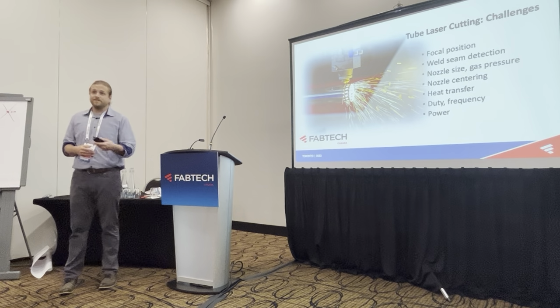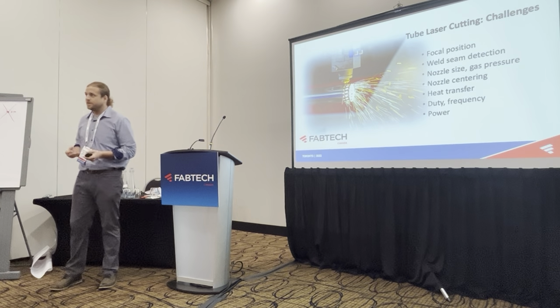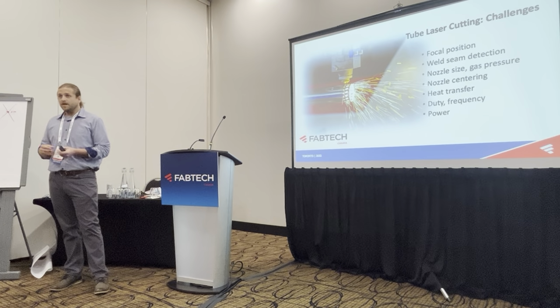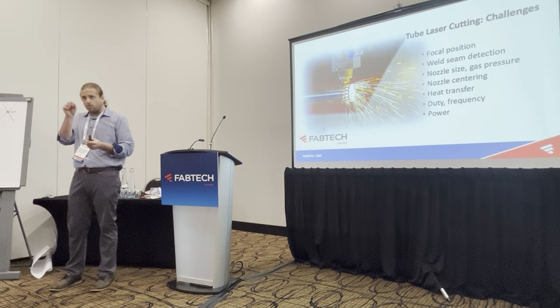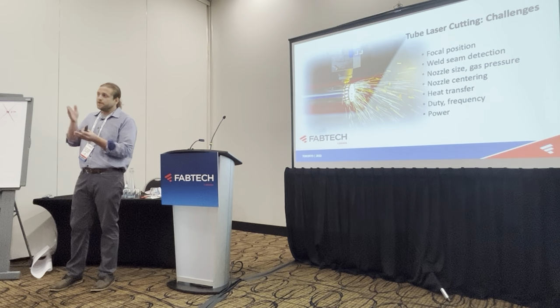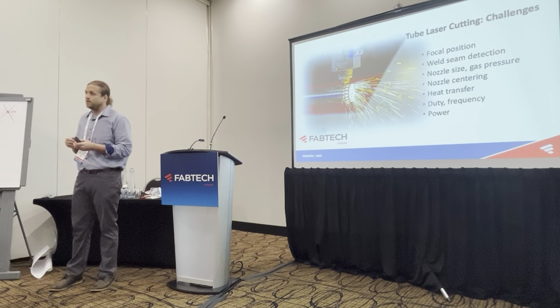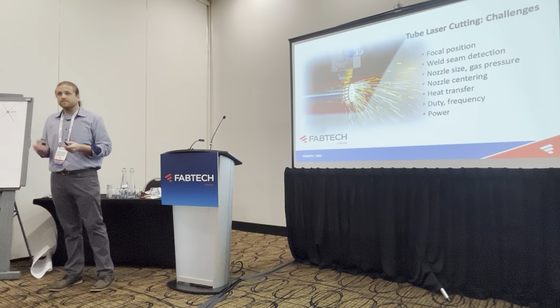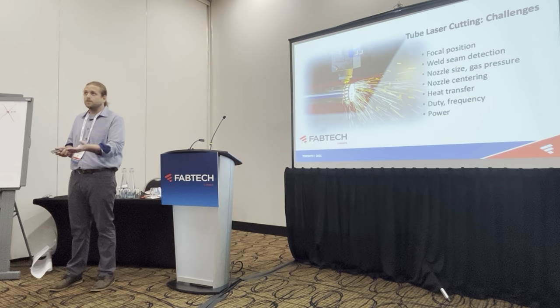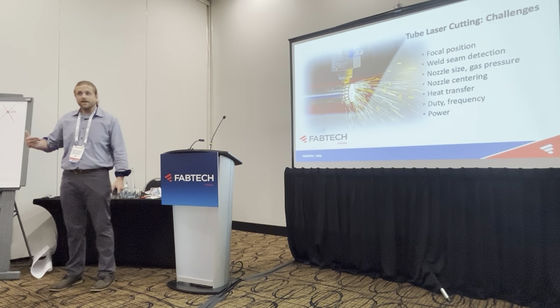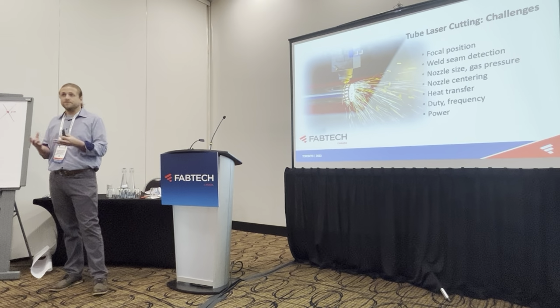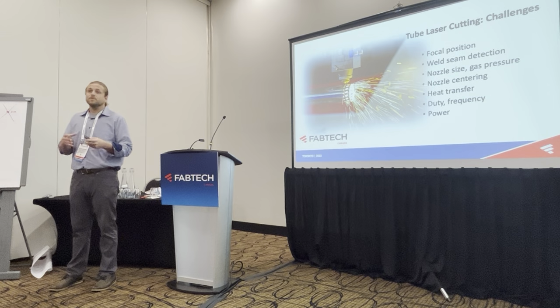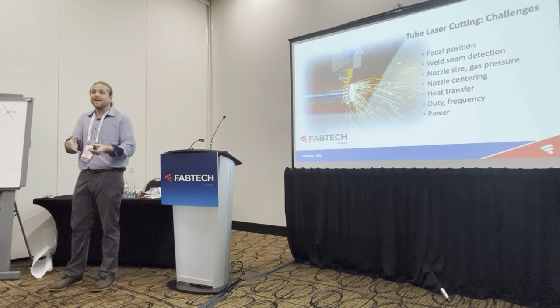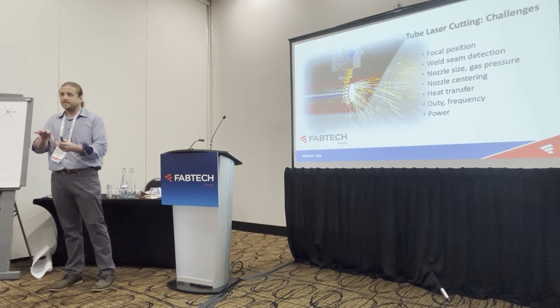Now aluminum, that's a different issue. Aluminum is a softer material, and as you're cutting it, it's really difficult to get rid of the burrs. With steel and stainless, you'll get a nice rollover bead from your dross. With aluminum, you get actual sharp cut teeth that you'll have to deburr, and you can't really eliminate them completely. You can dial your cut in to reduce them, but most of the time with aluminum, you're always going to have to do some kind of deburr operation. And then with stainless also, you have your weld spatter from cutting. A lot of customers are using stainless for some sort of fluid to go through or whatever it is. Sometimes you'll have to apply a weld anti-spatter to the ID of the tube before you even laser cut it to eliminate that from sticking to the ID of the tube as well.